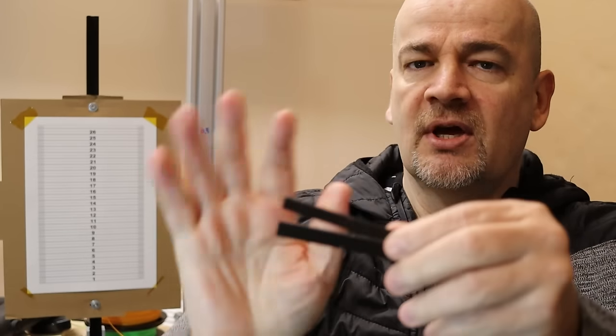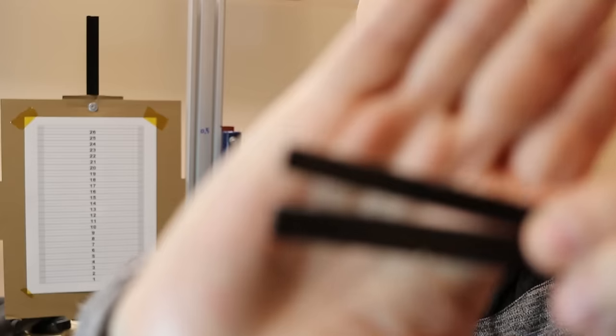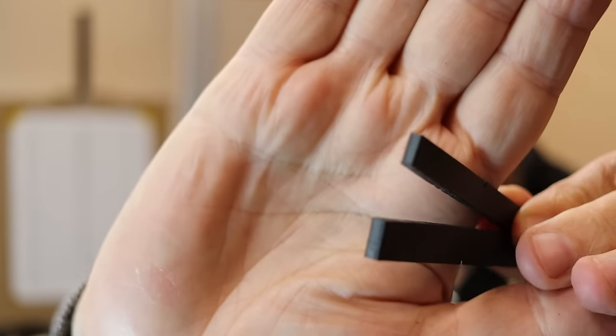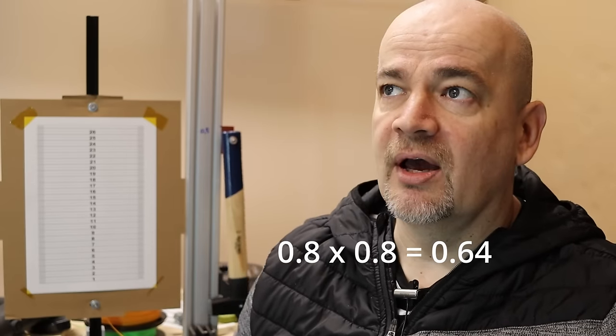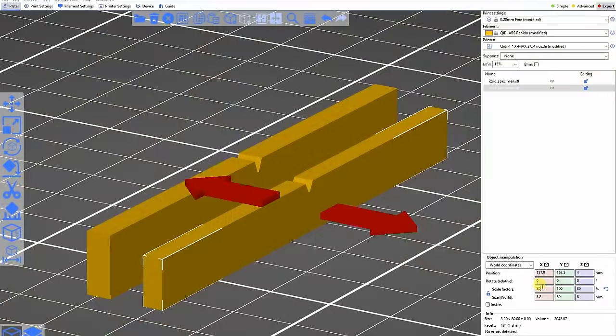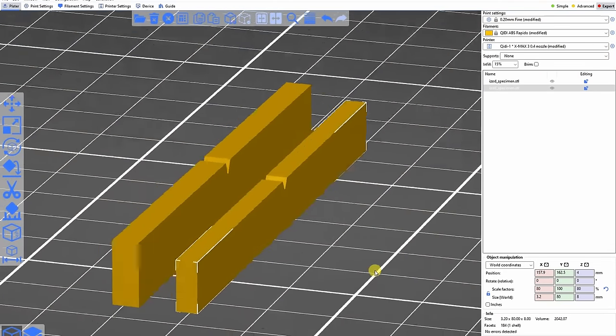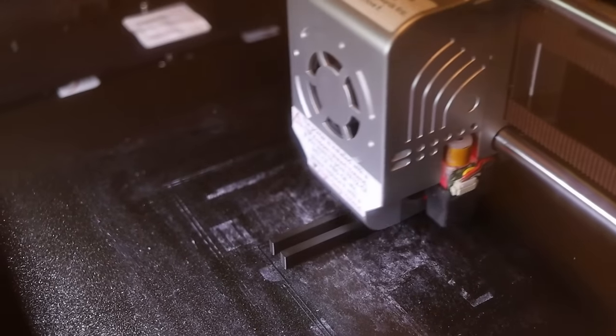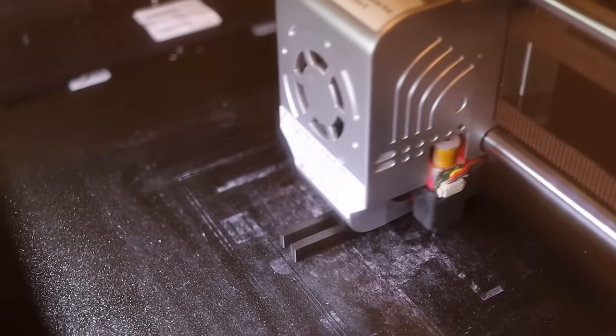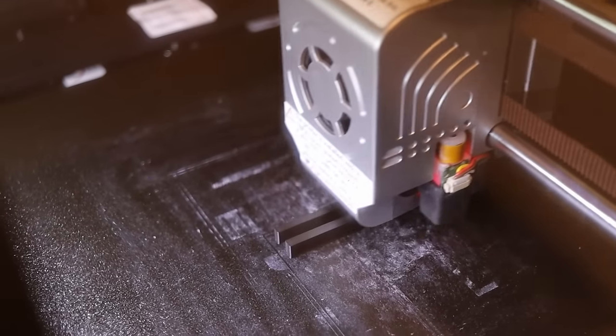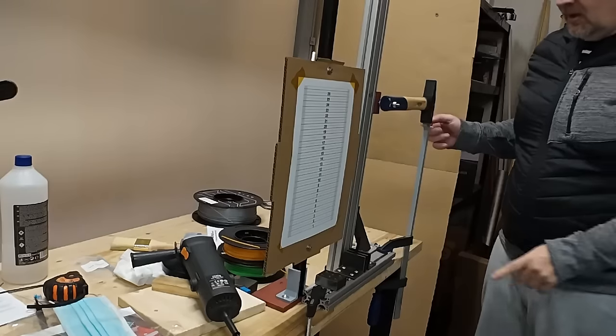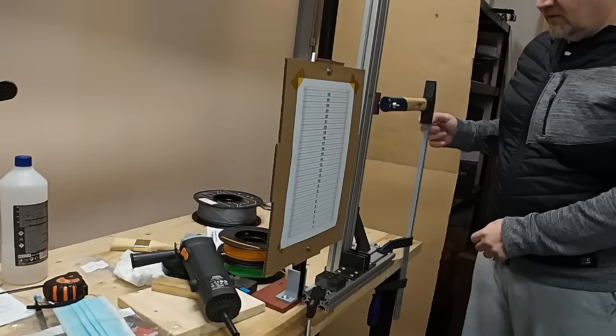I just couldn't stop here because I want to know approximately at least what is the maximal break load for this material because it was not even close to being broken with this half kilogram hammer. The correct method would be to replace the hammer with a one kilogram version. But I don't want to change my test equipment because it works great with most materials. Instead I'm using a different approach. So I reprinted these test objects and I reduced the dimension to 80% in two dimensions. So this means I reduced the cross section area to 64%. And I hope this will be enough to break it with this half kilogram hammer. Not 100% correct method. In theory it works, yes. But just to satisfy my curiosity, this will be fine for me.